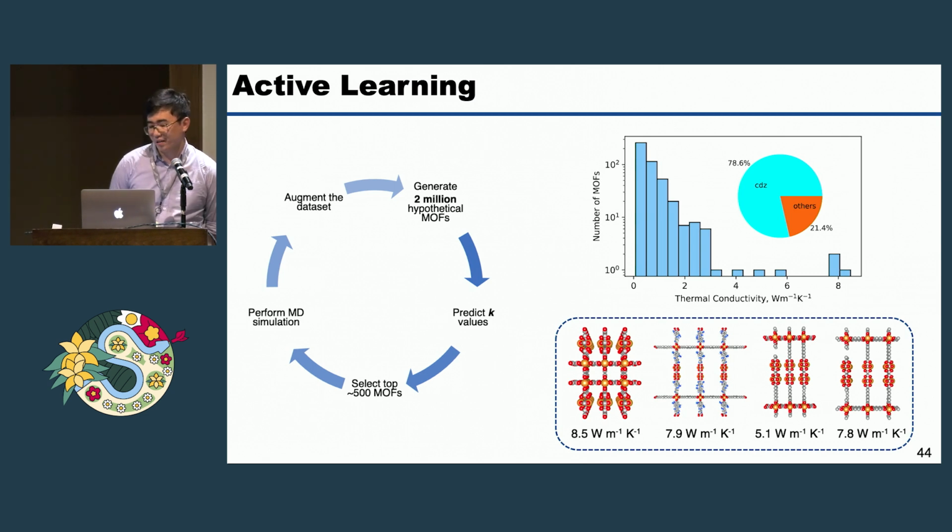Yeah, not many of them are stable. That's why we selected 2,000 of them, but 1,500 of them failed because of that problem. But 500 of them run fine because before running the thermal conductivity calculation, we optimize the structure. So yeah, we only select the ones that don't fail.